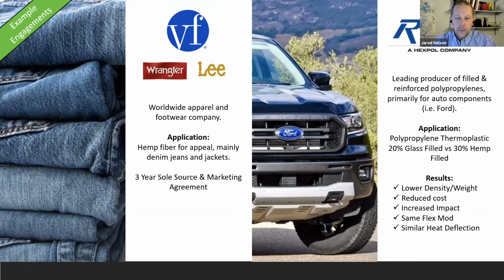So another engagement was with a company called RheTech. They are a leading producer of reinforced polypropylenes, primarily for automotive. And in this particular case, we took a polypropylene thermoplastic that had a 20% glass fill and upped it to 30% hemp, and basically reduced costs and improved or kept all of the key metrics the same.